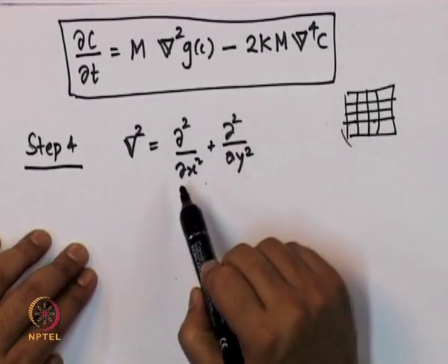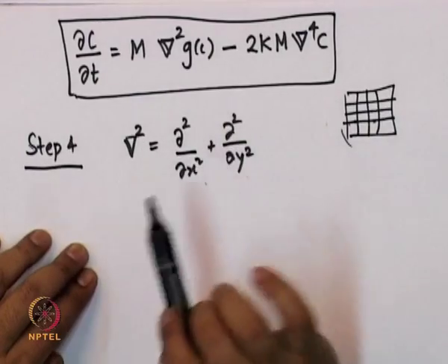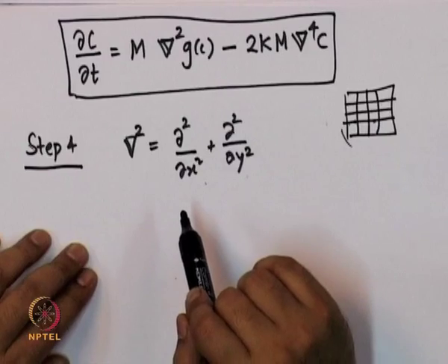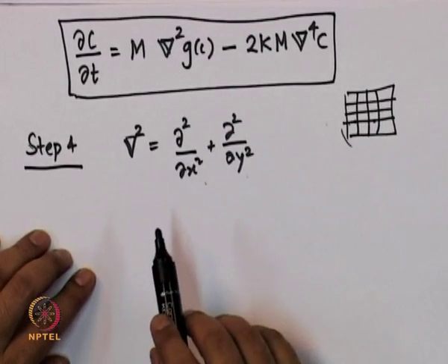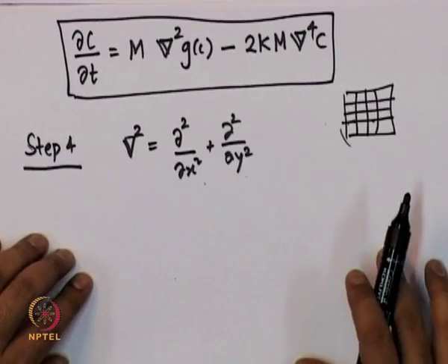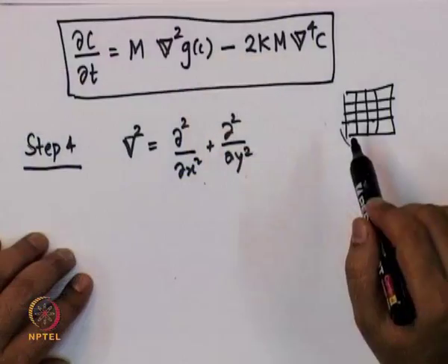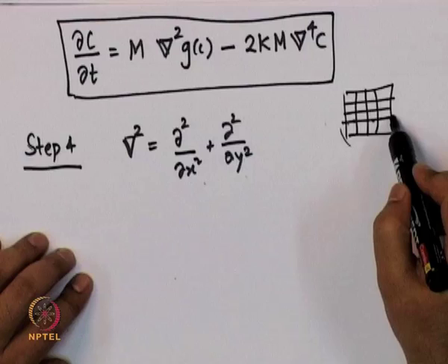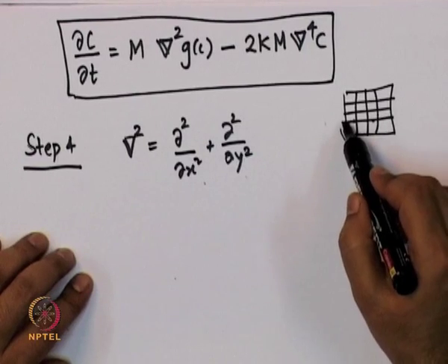So, in other words, doing a finite difference implementation of this is going to be very involved, but we are going to do a Fourier spectral implementation, a semi implicit Fourier spectral implementation. In that implementation, as we have discussed earlier, the periodic boundary condition is implicitly assumed. Periodic boundary condition means that there are no surfaces that we consider. So, all points have points to the left, right, top and bottom.